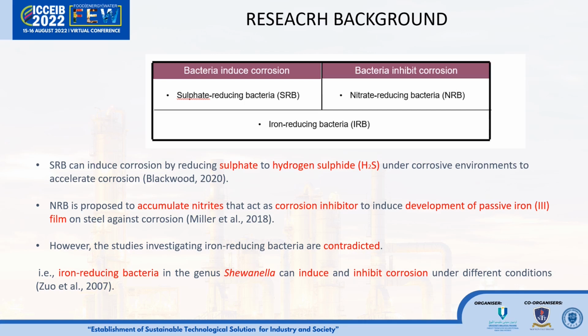Just now I mentioned the incident at Prudhoe Bay of Alaska in 2006. The researchers found that sulfate-reducing bacteria were highly damaging in MIC because they are capable of enhancing corrosion by reducing sulfate to hydrogen sulfide, creating a corrosive environment. In contrast, current studies reported contradicting findings for nitrate-reducing bacteria, as these nitrate reducers are capable of accumulating nitrites as the product of nitrate. These nitrites help to develop a passive iron 3 film against corrosion. Yet, current research interest has started to look at iron-reducing bacteria species in the genus Shewanella, because Shewanella are postulated to enhance and inhibit corrosion under different experimental settings.